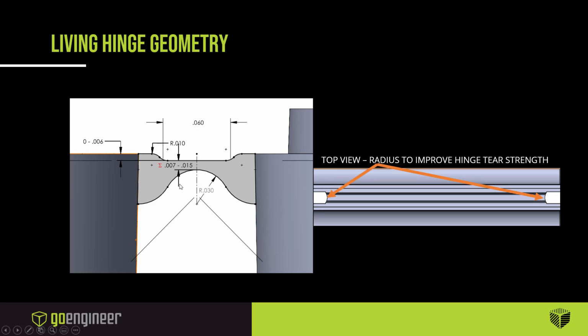The full radius at the bottom, that 30 thousandths full radius, is important. It allows the material to flow through there properly, and it also allows the part to hinge all the way over and bend at the apex of that 30 thousandths radius. So it'll fold over to a flat. If we look at the top view over here on the right, if we radius those edges, it'll actually improve our hinge tear strength as well. So that's part of the design that goes into it.